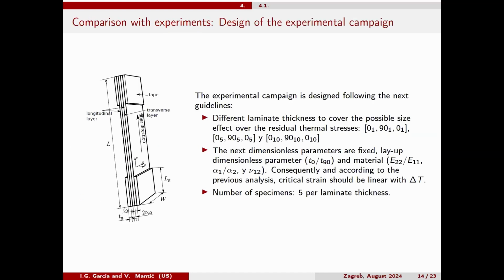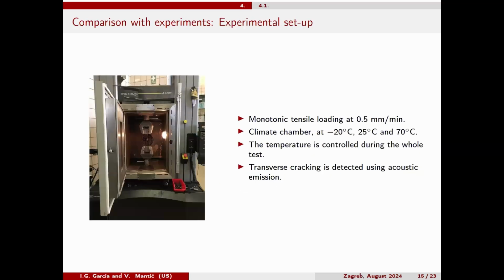So we fabricated 5 specimens per laminate thickness, and the others are the classical ideas. Concerning the experimental setup, we use a monotonic tensile testing machine, the classical mechanical one, with a strain rate that is very classical also in composite. But the interesting thing, the new thing, let's say, is that we are using a climate chamber in order to